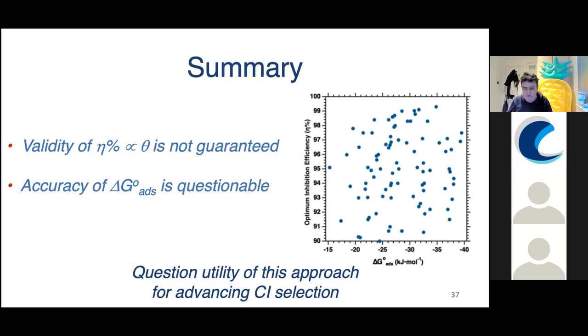And just to convince anyone who's wavering, I'd like to show this. We've said in some other work, okay, we accept that delta G isn't perfect, but maybe we can use it as a description. Maybe it's not really delta G, but it's a semi-quantitative descriptor of the adsorption. We've looked in the literature for as many delta G's as we could find in acidic conditions for different inhibitors and plotted optimum inhibition efficiency, between 90 and 100 here, versus delta G of adsorption, the standard Gibbs energy, going from minus 15 to minus 40. That's the typical range you find in these publications.